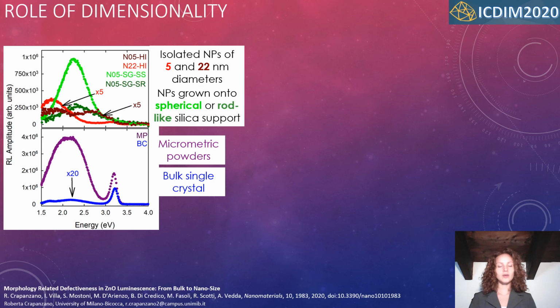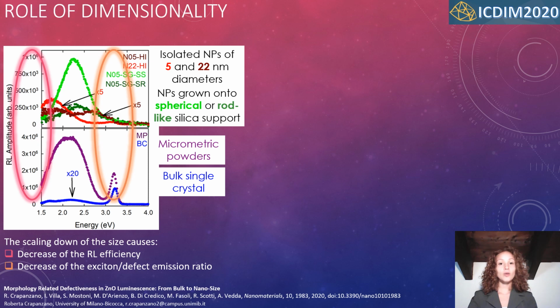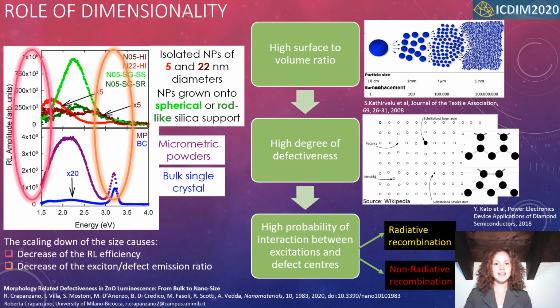To study the role of dimensionality, we will focus on the absolute radioluminescence amplitude. The overall emissions of the nanoparticles are about 1-2 orders of magnitude smaller than those of the micrometric powders and the bulk single crystal. Moreover, the exciton-defect emission ratio decreases as the size scales down. These results suggest that the degree of defectiveness is higher in nanometric samples with respect to that of the bigger ones. In fact, as the size scales down, the surface-to-volume ratio increases.